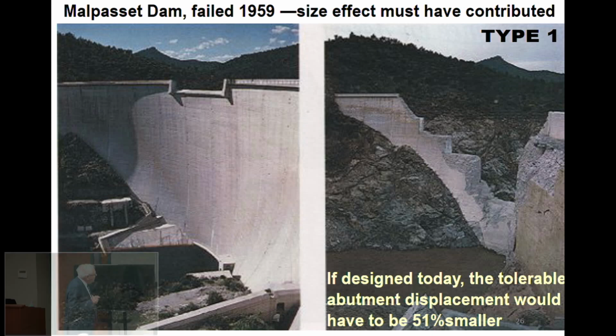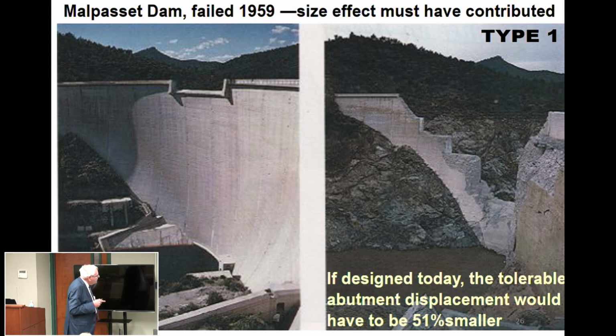I would like to mention one case of many where this made a difference. We analyzed in detail the failure of Malpasset Dam in France in 1959, which was the tallest and thinnest arch dam in the world. It failed at the first filling. And this is what it looked like afterwards. The flood wiped out totally the town of Fréjus, with several hundred people dead. What we can say today is that if it were designed today, based on this kind of analysis, the tolerable movement of the foundation would be about 51% smaller.